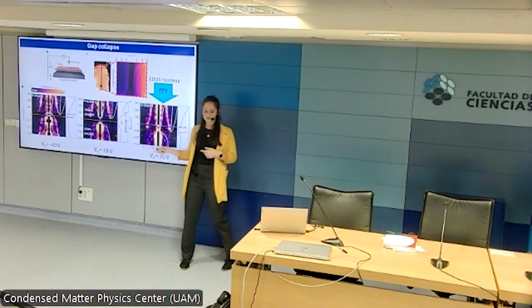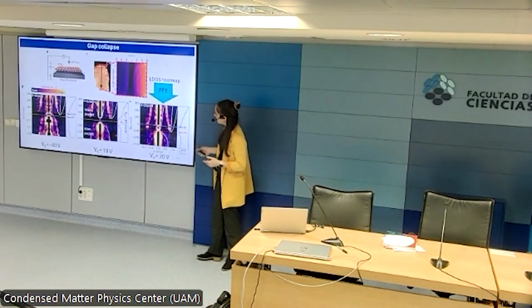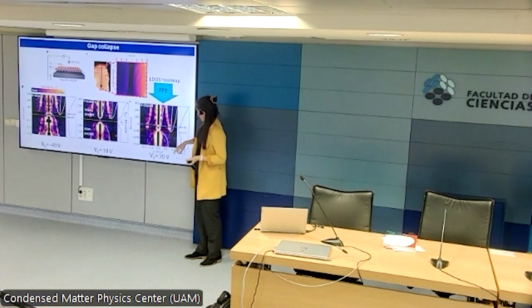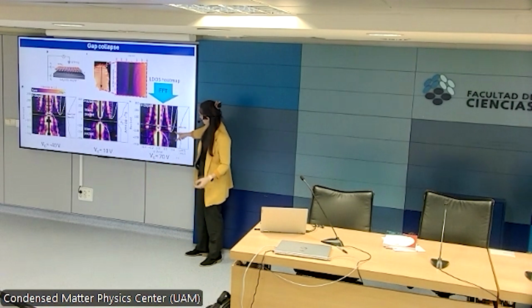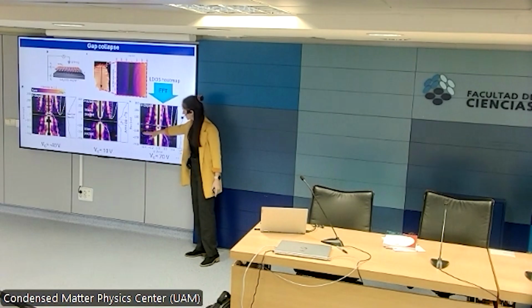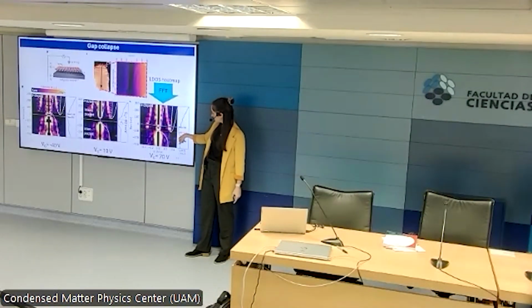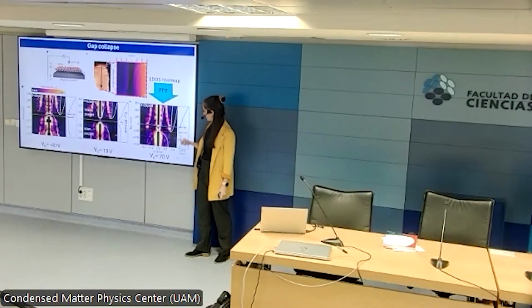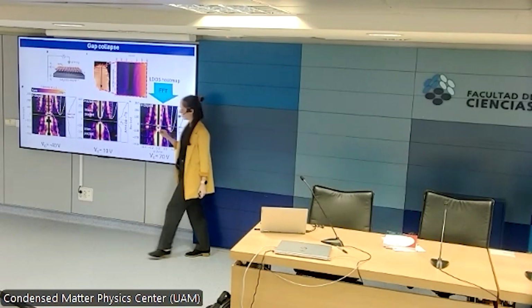If we now gate the system on one end or the other, the picture looks very different. Let's look at this first. This is positive bias. You can see that the band gap has all but disappeared. Wherever the band gap was, which is where the bands now cross, there's just a dip that is the charge neutrality point, and the Coulomb gap appears at the Fermi level.